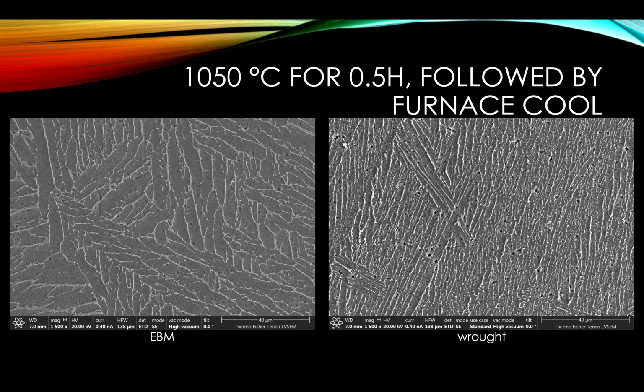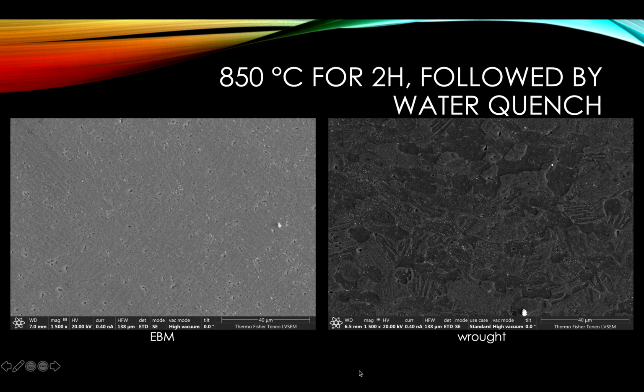Well, the wrought sample only shows that the grain size is becoming coarser, not so much difference else. And for the 1050 Celsius followed by furnace cool, both of them have this laminar microstructure, except the EBM ones are much coarser than the wrought ones.